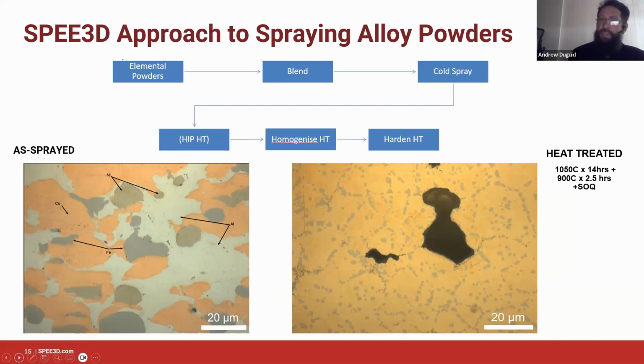Well, we heat treat it, and we heat treat it reasonably aggressively. But what we wind up with is something like what you see on the right-hand side there. You can see that all of the individual particles have lost their identity, and you're seeing a more or less homogeneous matrix, with the classic nickel aluminium bronze. There's some high temperature kappa phase there precipitated out on the grain boundaries.